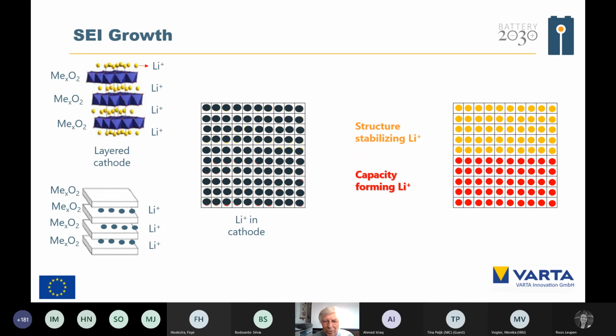So let's have a look at that mechanism. We have layered materials like NMC, for example, that are the metal oxide layers. In between, we have the lithium. So, here we have a view on all lithium in the cathode. And we divide all lithium into one part that is structure stabilizing the cathode material. If we have no lithium between those layers, all lithium is outside, then the structure is collapsed. So the layers are going together. So we need a part of the lithium as the so-called structure stabilizing. And the other part, that is the capacity forming.